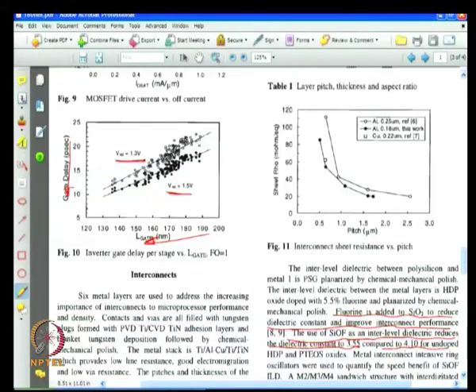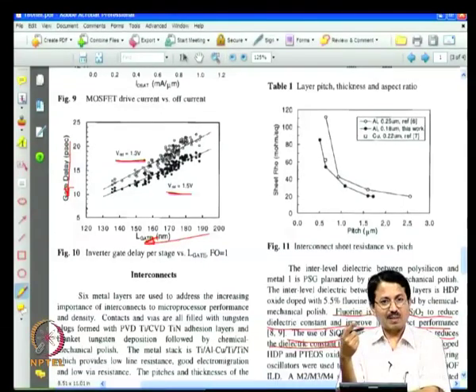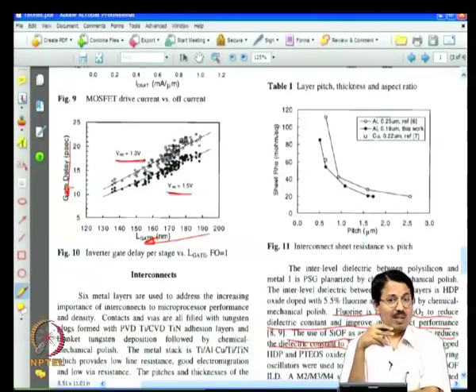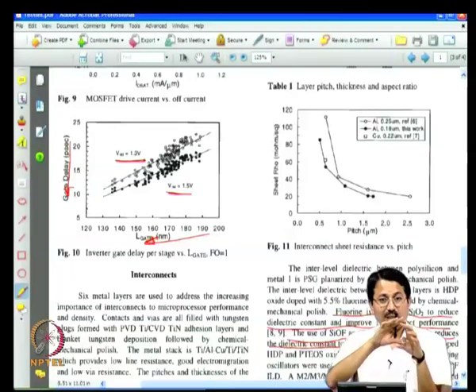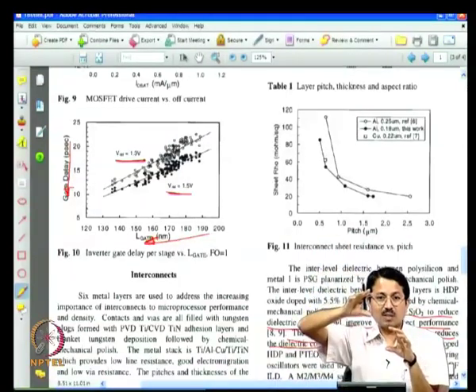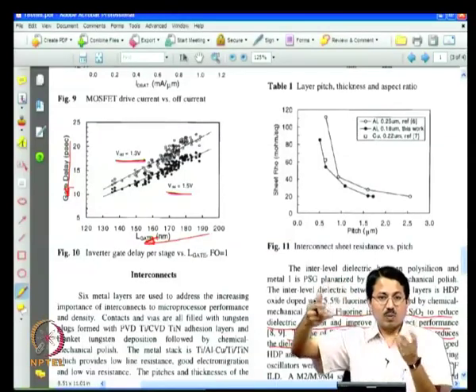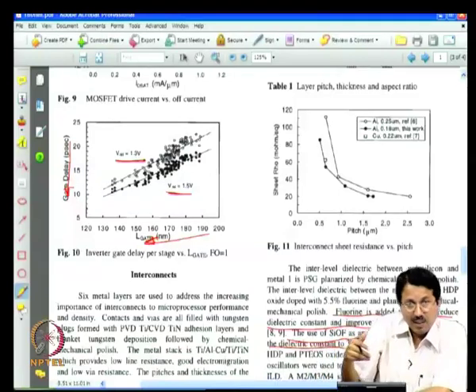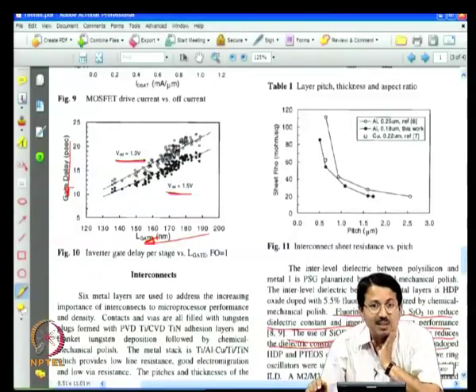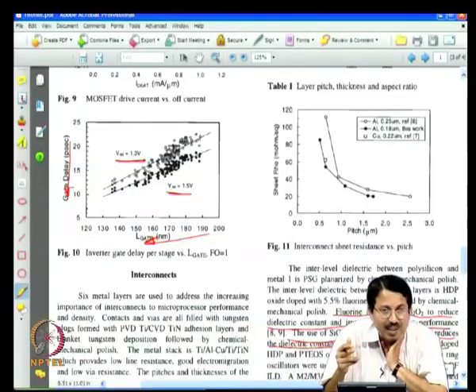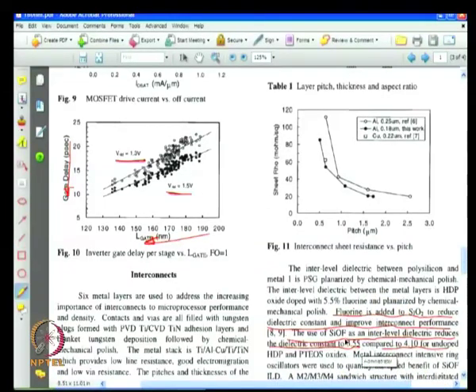You see, thermal oxide, if oxide is grown at, let us say, high temperature, 1000 degree centigrade, then its dielectric constant is more like 3.9. That is what we used earlier when we were talking of gate dielectric, 3.9, we round it off to 4, but here we say 4.1, because this oxide is not thermally grown, it is a deposited oxide, because you already have a metal line, and on top of the metal line you have to put oxide. So, there is no silicon to grow oxide, you will have to do a chemical vapor deposition of the oxide, and invariably these oxides which are done at low temperature, because you already have a metal, tend to have a little higher dielectric constant, and hence the dielectric constant is of the order of 4.1. After fluorine doping, it comes all the way down to 3.55.